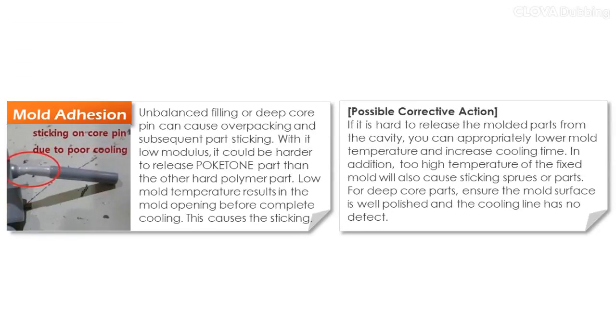Unbalanced filling or a deep core pin can cause overpacking and subsequent part sticking. With its low modulus, it could be harder to release a polyketone part than other hard polymer parts. Low mold temperature results in the mold opening before complete cooling. This causes the sticking. If it is hard to release the molded parts from the cavity, you can appropriately lower mold temperature and increase cooling time. In addition, too high a temperature of the fixed mold will also cause sticking sprues. For deep core parts, ensure the mold surface is well polished and the cooling line has no defect.